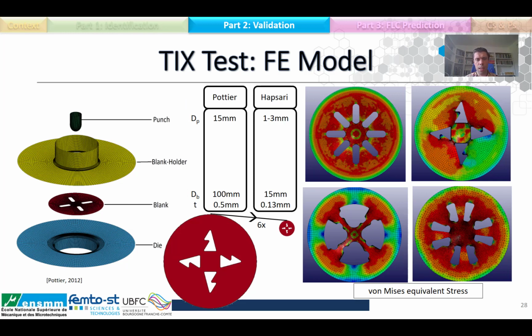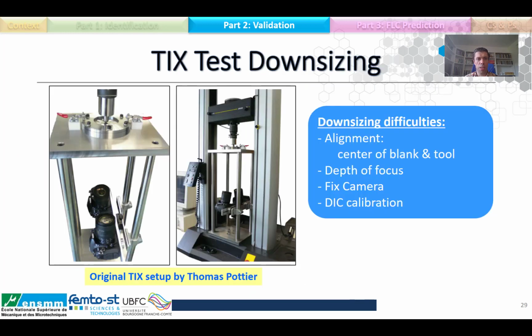So the TIX test was simulated numerically by a finite element model using the material parameters obtained with the micro-indent method and for different grain sizes. For the experimental part, with the downsizing of the TIX setup, we are facing some difficulties. First, the alignment is hard to obtain. The alignment between the punch and the experimental setup, considering that the punch is fixed to the crosshead of a tensile test machine, and the setup is fixed on the mobile part of the tensile machine. The alignment between both is not good enough, especially with very small blanks.